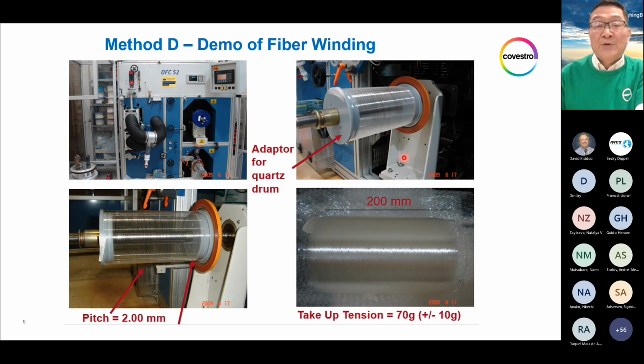So this is in our actual laboratory, where we wind the fibers according to all the parameters in method D of the IEC technical report, right? It has a well-defined pitch, well-defined take-up tension, and layer by layer, the next layer has a different winding direction to intentionally create those cross fiber points that simulate the fiber-fiber interaction that could cause microbending loss. So this is the key reason why we picked method D among the 4 methods.